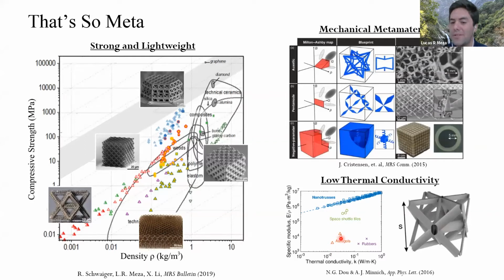So if you look at materials like aerogels, that's what aerogels do. But aerogels have this kind of stochastic architecture. They form randomly in whatever chamber you use to make them. And if you take effectively the same amount of material, but you intelligently architect it, you can get orders of magnitude better stiffness performance than you do with an aerogel.